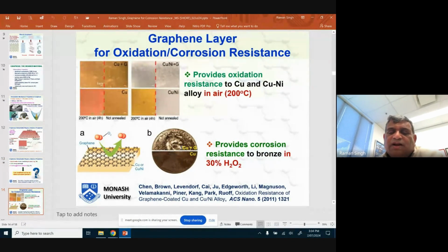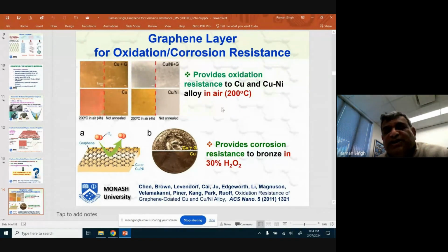The first work on this topic was carried out in Rod Ruoff's group when he was in Texas. And what they did is that they took pure copper nickel alloy, and graphene coated copper nickel alloy and pure copper. And they exposed all the samples to air at 200 degrees Celsius. As you can see, copper and copper nickel alloy, they changed color because they oxidized, whereas graphene coated one didn't. That's why no change in color.